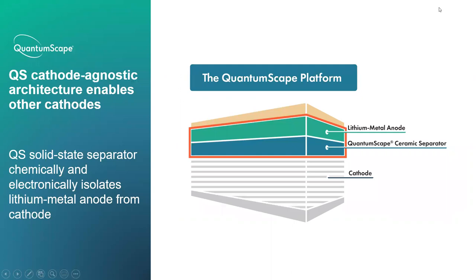So there are some other benefits to this. Most of the innovation here is around two parts of the system: the ceramic electrolyte and the lithium metal anode that goes on top of it. It turns out that you can use almost any cathode with this design that you want. So I alluded to this earlier. You can take the highest energy cathodes that are available and make a cell that would be fantastic for long range, for example, in a vehicle. But you can also use something else. So if lower cost is more important, you can take a cheaper cathode material, and you still get the benefits of higher energy density and better power. As cathode research evolves and new materials are discovered, you can also take advantage of those and continue to evolve this platform.